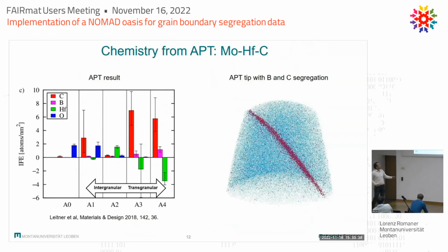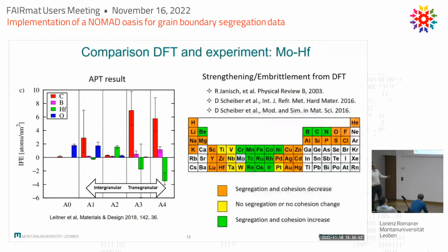And so one can actually understand why these grain boundaries are stronger, because they have a different chemistry, first of all, and we can predict from DFT, these are DFT simulations, as we have seen before now from Molly, that boron and carbon are really good elements also here, and oxygen is a bad element, and we see that the chemistry here is just more favorable in terms of the cohesion, right? So cohesion, I think, is a topic which we can understand very well.